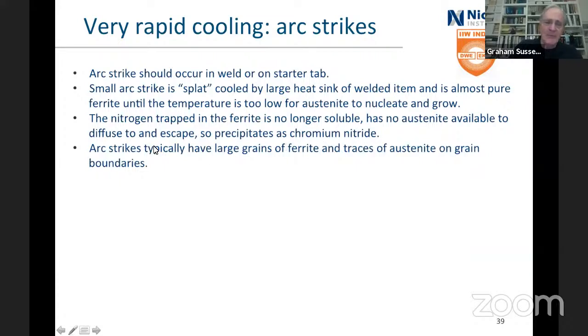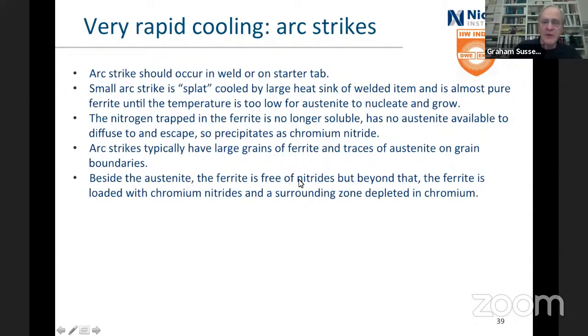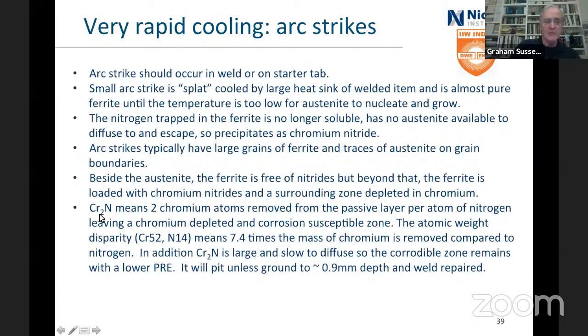And that is bad. Typically, experimental work showed that you get large grains of ferrite and then traces of austenite on the grain boundaries, and beside the austenite, the ferrite is free of nitrides. But beyond that, the ferrite is absolutely loaded with chromium nitrides, and the surrounding zone around those nitrides is depleted in chromium. Oh dear, we're relying on the chromium to give us corrosion resistance, and it's locked up with nitrides. And in fact, Cr2N, 2 chromium atoms, so about 7.4 times the mass of chromium is removed compared to the nitrogen. And in addition, chromium nitride is pretty big, so it's slow to diffuse, so the corrodible zone with low chromium remains with lower PRE.